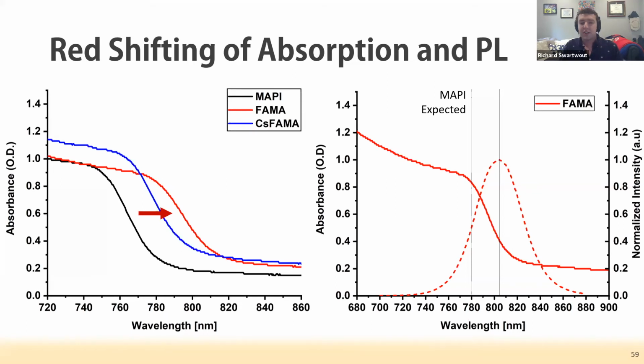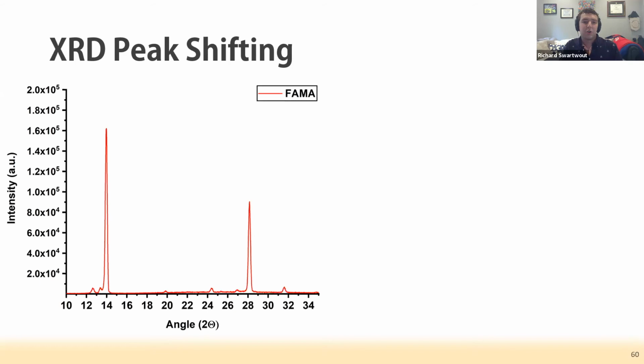You can also look at X-ray diffraction, which is a chemical fingerprint of crystallographic materials. I want to make abundantly clear that the FA-MA-based films are very strictly perovskite with relatively little off phases, just a bit of hydrated phase up near 12.